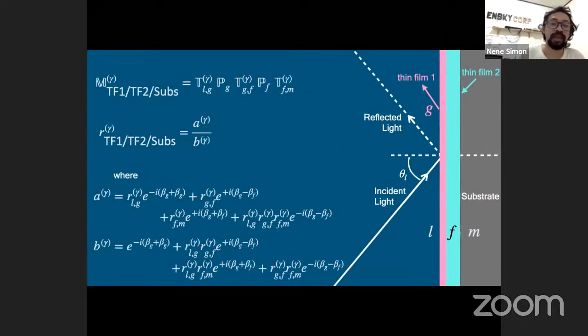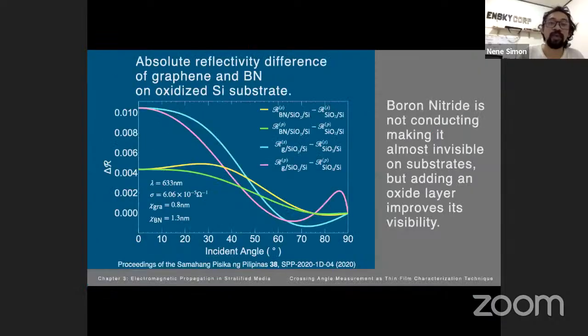And then from here, we have an effective transfer matrix given by this equation, and the effective reflection coefficient is given by this ratio, A gamma over B gamma, where A gamma and B gamma are described by these lengthy equations here. So you might be wondering why oxidized substrates. It is so because incorporating an oxidized substrate, incorporating a thin film, increases the visibility of a 2D material.